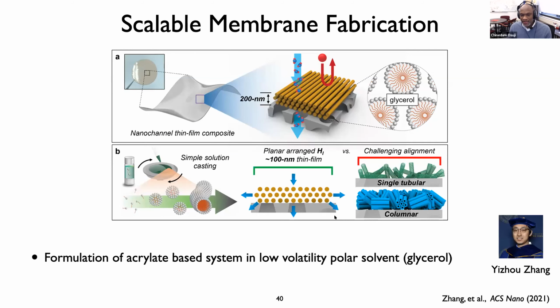What we've been able to show more recently, this is a paper that just showed up, I think, last week in ACS Nano, and this took quite some doing, but what we've been able to do is to transition similar ideas from 20 micron thick films produced by mechanical pressing to films that are now on the order of 200 nanometers in thickness that are produced using a solution processing method. And the difference is a non-trivial one. This is a factor of 100 change in the thickness of the selective layer, which for a given pressure drop corresponds to a factor of 100 in the flux, in the volume of water, for example, that might be produced by this membrane.